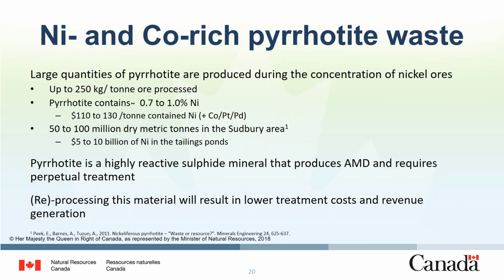The first reason, large quantities of pyrrhotite are being produced at operations during nickel extraction and concentration, and there's significant value in this material with an average grade of 0.8% nickel. At $12 per kilo, that's $100 per ton rock. With negligible mining and milling costs, it's simply slurry and pump. Some of the historic material may contain more than $200 per ton in value, and in addition, some of the pyrrhotite tailings have significant cobalt PGE content, making it even a richer material.